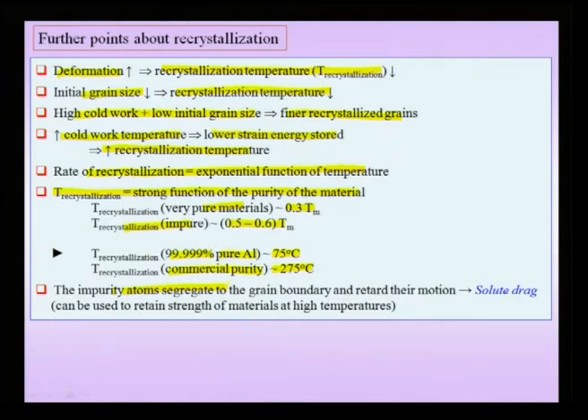The reason for this is that the impurity atoms, and all the impurity atoms need not always be equally soluble in the lattice or the grain boundary. Many of them may have poor solubility in aluminum, for instance, or the lattice, and therefore they typically tend to segregate at grain boundaries, and these typically retard the motion of the grain boundary itself, which is called solute drag, and this can be used to retain the strength of materials at high temperatures.